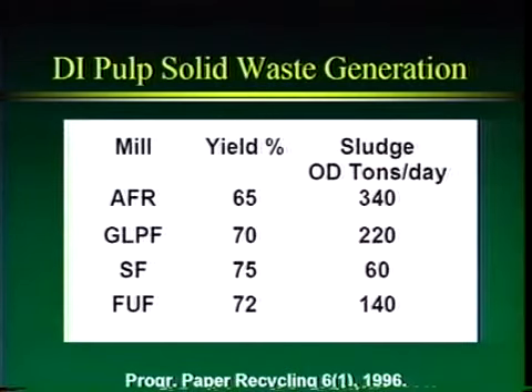Just as an example, and this is a little exaggeration, but this was published in Progress in Paper Recycling in 1996, Volume 6, Number 1. Here are 4 different de-inking mills in the United States, with abbreviations for them. You can see that these mills are taking mixed office waste, de-inking it, and making printing and writing grade quality papers out of them, high brightness, low mechanical pulp. Yields around 65–75%. So we're only getting about 2/3 to 3/4 yield.